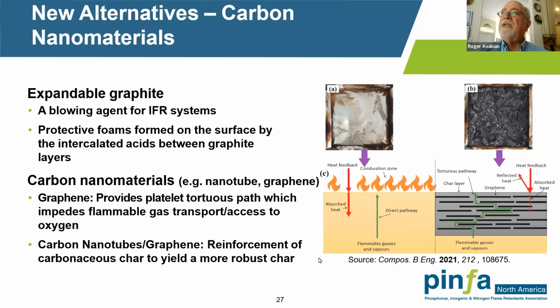Because there are certain tests where, for instance, in large scale tests for pallets and things like that, in fact, one of the tests where they actually spray on water, you need to make sure that the water doesn't break down that char and then basically release flammable gases and allow oxygen ingress in. So in many of these types of systems, and depending on the test, the integrity or the strength of the char is very key.